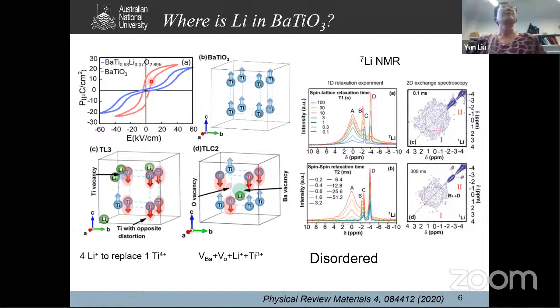So where will the lithium go? If we do XRD and neutron scattering, because lithium is a light element, XRD doesn't give you the intensity, the structure information. We also did NMR and ESR, electron spin resonance spectra, and we found that in this case, actually nearly 70% of the lithium is located in the glassy phase. Okay, so they are located in the grain boundary of the ceramics and in the amorphous phase they form.